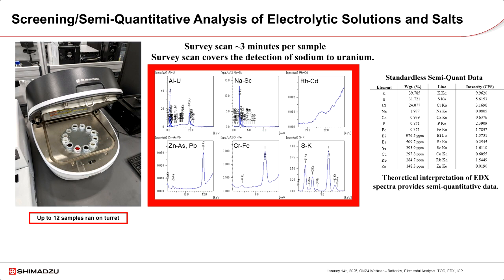Each sample was analyzed with what is known as a survey scan, which covers the periodic table from sodium to uranium. In this case, the survey scan takes approximately 3 minutes per sample. Note that even without a method that implements external standards, you can still get an idea behind the elemental composition of your material. In this case, we call the data semi-quant data because it was procured without the use of external standards. One nice feature of EDX is that it is still possible to get an idea behind the elemental composition of your material even without the implementation of standards.